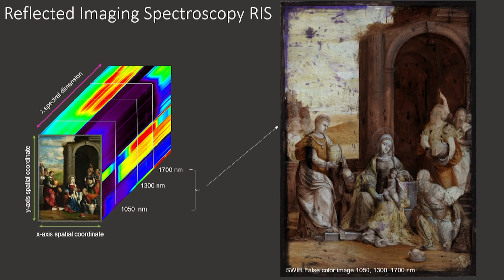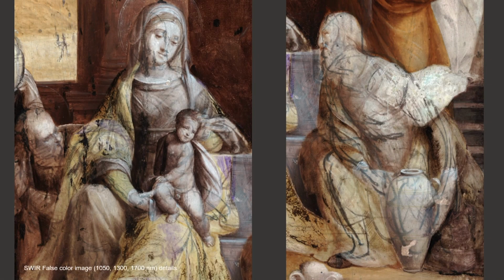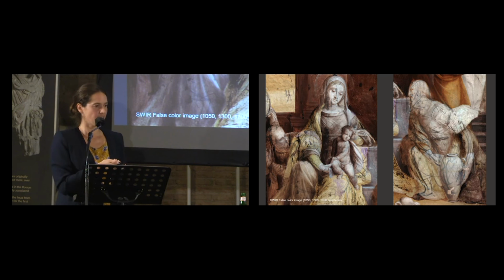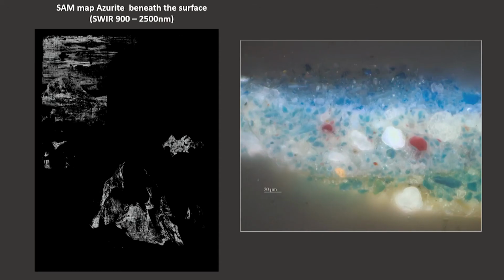The data cube can also be sliced at different wavelengths, and getting 3 of them and combining them in a false color infrared was quite useful. In the 2 details, I hope you can appreciate the underdrawing that we were discussing before, very visible and very tormented freehand underdrawing in a liquid medium. And so we could nicely, with reflected imaging spectroscopy, visualize the presence of the underlayer of azurite, for example, and this matched the information we had from the sample, that azurite is present in the underlayer, in the 2 underlayers. So this, and here, mixed with lead white and some red lake.